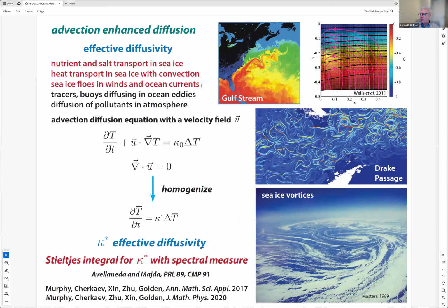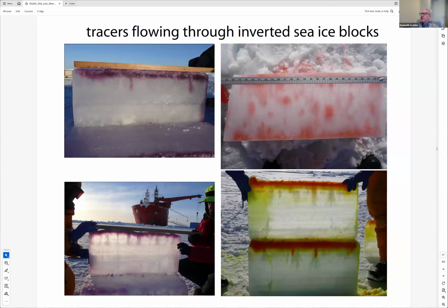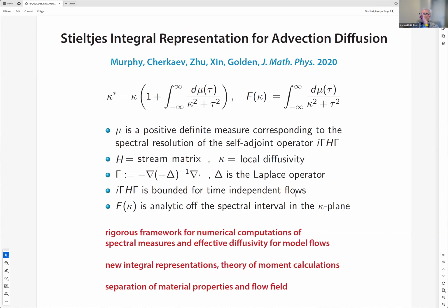Okay, so at the mesoscale, advection diffusion problems are also very important in the sea ice business. So here we have the advection diffusion problem, homogenize this, and Andy Majda and Marco Avellaneda were the first to take the functional analytic framework that George Papanicolaou and I developed and apply it to develop Stieltjes integral representations for the advection enhanced diffusivity. Here's some of these tracers moving around in the ice. These are some experiments that I did a long time ago. The Stieltjes integral takes a slightly different form, where instead of the geometry of the composite, it's the geometry of the velocity field that gets embedded into the spectral measure, but it has all the same basic mathematical hallmarks.